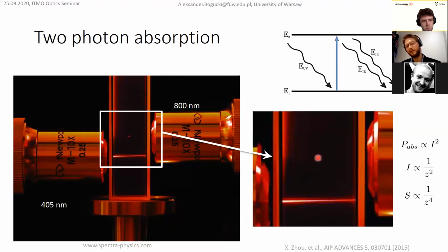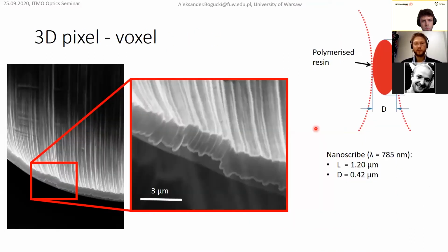photoluminescence occurs in this very small area, and that's because the two-photon absorption is proportional to the square of the power, and when we have a Gaussian beam, then we obtain a lateral size which depends on the fourth power of the characteristic scale of the beam. So we obtain an increase in resolution. So the smallest polymerized volume is called a voxel. This is like a pixel, but in three dimensions.